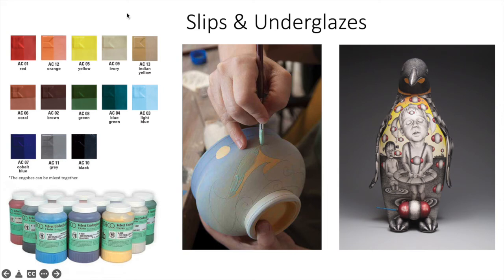What do we use for decorating? Well, there's a lot of things. We can use glaze. We talked a little bit about that, but the most predictable material that you can use are underglazes or slips, and basically that's a liquid clay with a mineral pigment in it. So a slip or an engobe are usually more simple, just kind of like clay, water, maybe a deflocculant, and the mineral pigments. Versus the underglazes are going to be a little bit more engineered to have more predictable and versatile results.